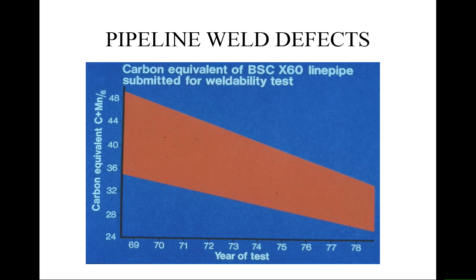And constructional steels have undergone quite a change over the years. This is between 69 and 78, but the same thing has gone on since then. So the carbon equivalent has come down for the same X60 specification. And weldability has improved across that period because we've cut the carbon down and we've made it less likely that these brittle phases will form. So we have, over a period, improved the material that meets the same specification.